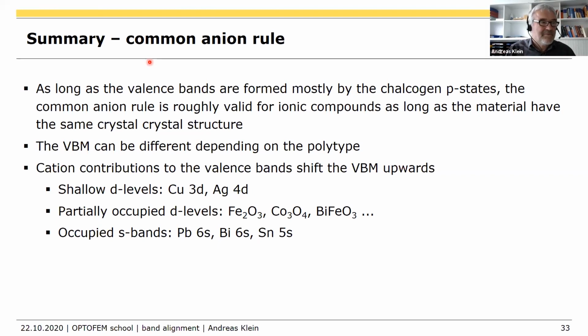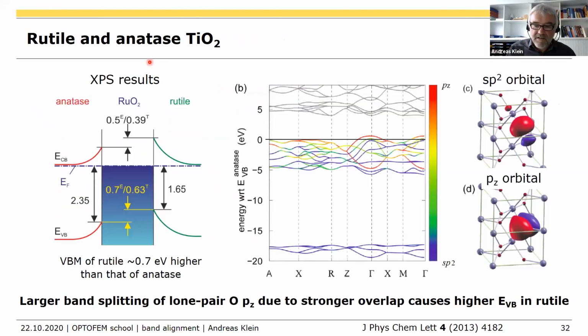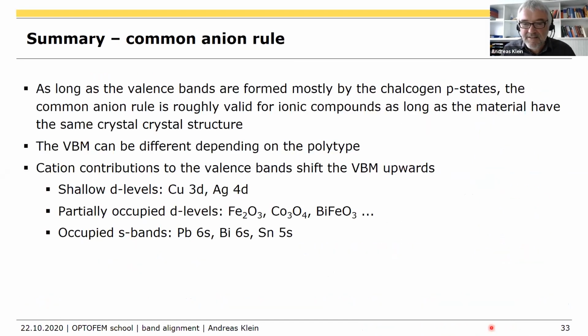you can distinguish the anatase and the rutile phase from the distance between the valence band maximum and the core levels. So this is also explained in this publication. And also we have some structural characterization. Well, for the single crystals, it was very clear. But for the thin films, they're usually anatase, and there we can distinguish that very nicely. I guess we also measured some films from Juan Biscard, who was our first speaker. So we didn't make those ourselves.